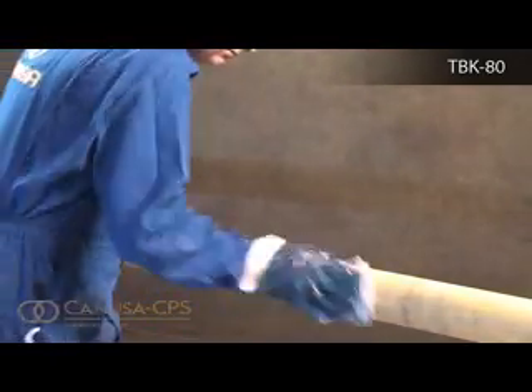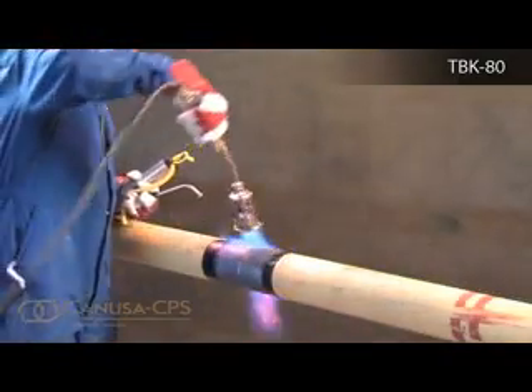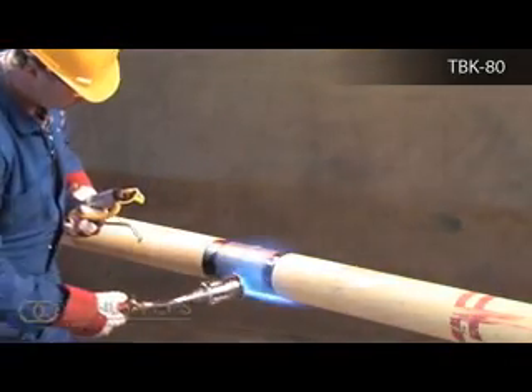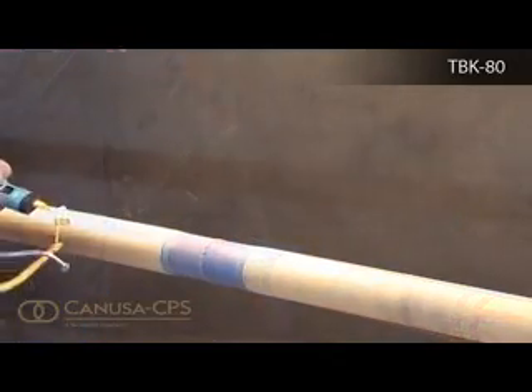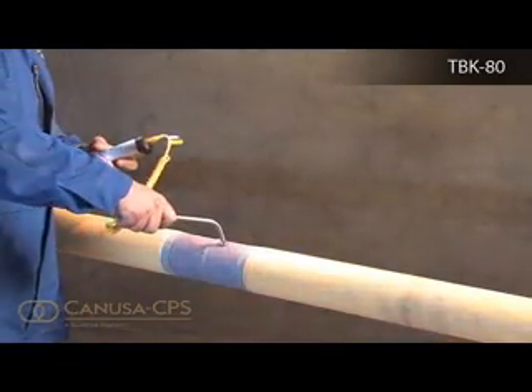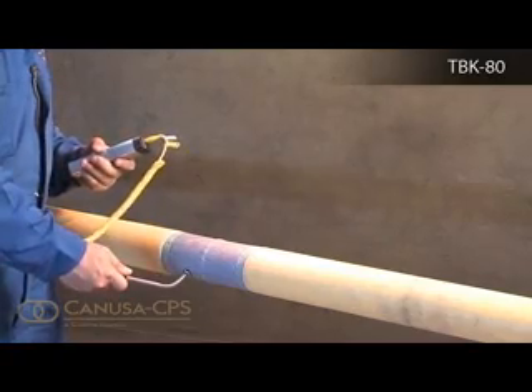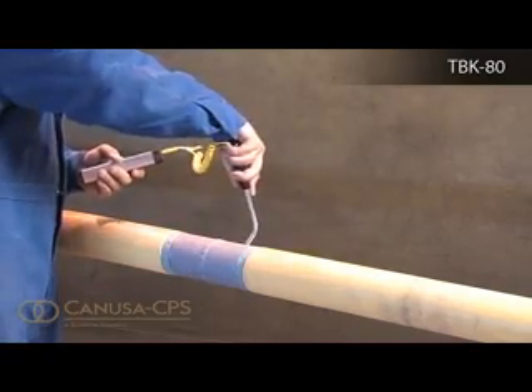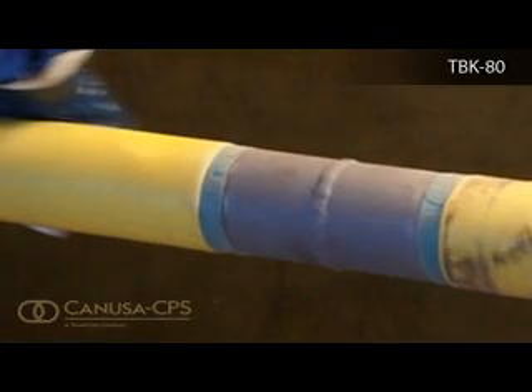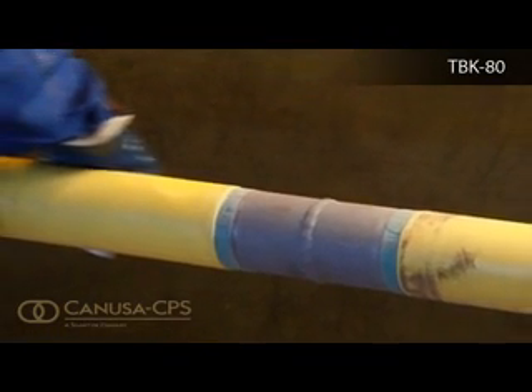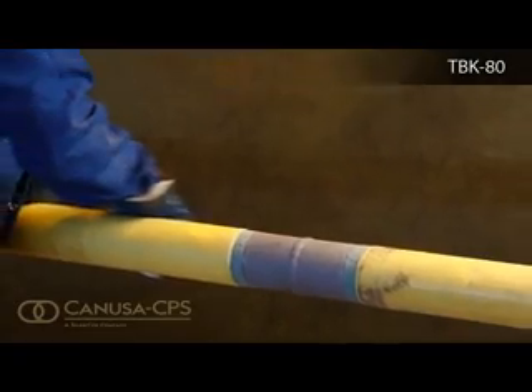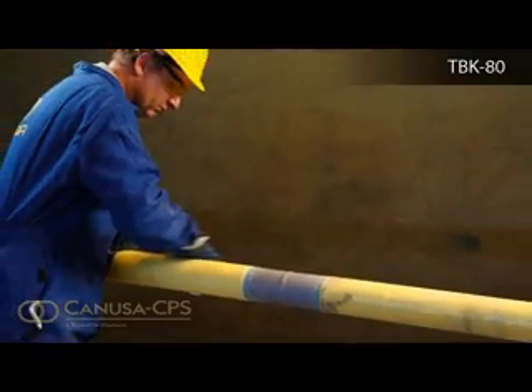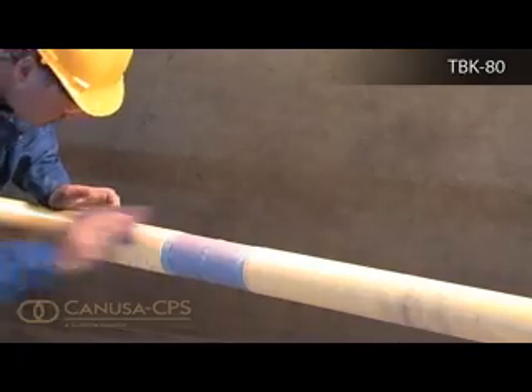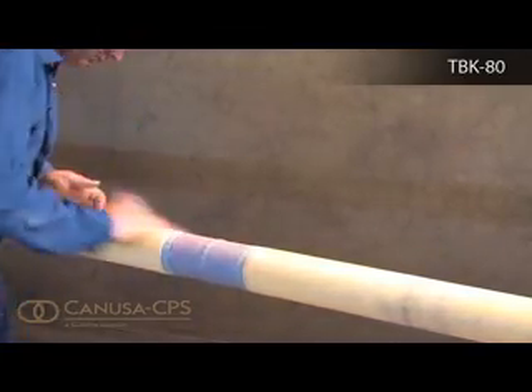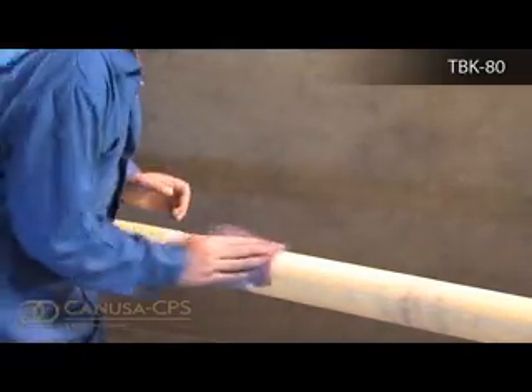Warm the joint area up to 40 to 50 degrees Celsius before grit blasting to remove any surface moisture or volatile contaminants. During high winds or cold ambient conditions, such as lower than 15 degrees Celsius, pre-warm the joint area to 70 degrees Celsius before grit blasting. Thoroughly clean the weld area with a sand or grit blaster to near white metal, SIS-SA 2.5 or equivalent. Abrade the mainline coating adjacent to the weld area to a distance 50 millimeters beyond the sleeve width.